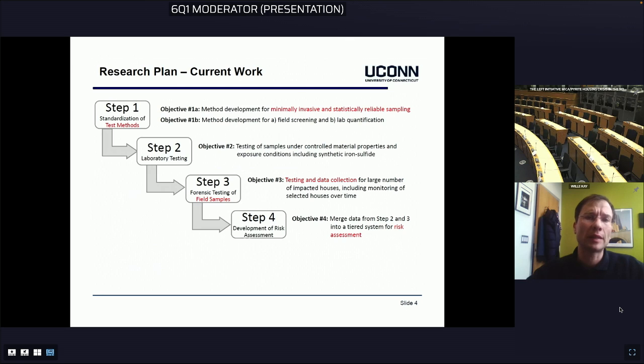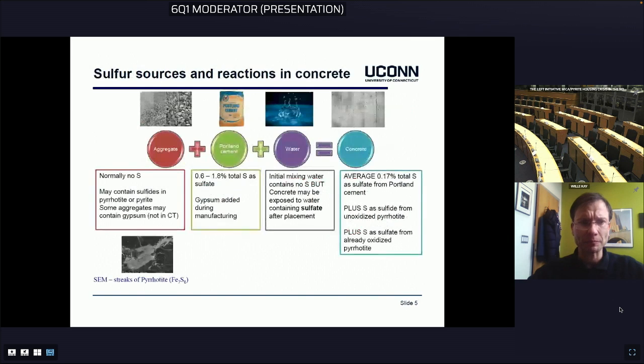Step 2 focuses on laboratory testing, where we mix our own concrete and set up a specific laboratory test where we can isolate parameters under controlled conditions. Step number 3 focuses on field sampling, forensic testing, to now, with the developed test method and sampling, develop a larger database where all data has been collected under similar conditions, so we can really compare apples with apples. And then step 4 is where all of this effort leads into the development of a risk assessment framework.